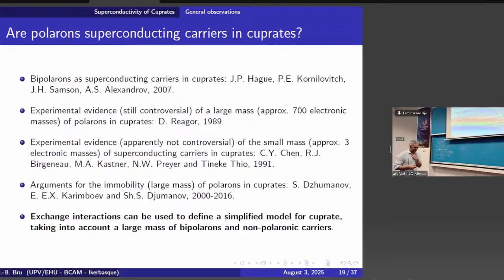The problem with that is that the effective mass of the bipolaron is supposed to be large. It makes it unlikely that they participate in the quantum transport. Also, the effective mass of the charge carrier particles is not so small, not so big, 3 or 4 times the electronic mass, whereas the bipolaron mass, for example, is estimated at 700. And so the bipolar ionic particle does not seem to be a very good candidate as a charge carrier.